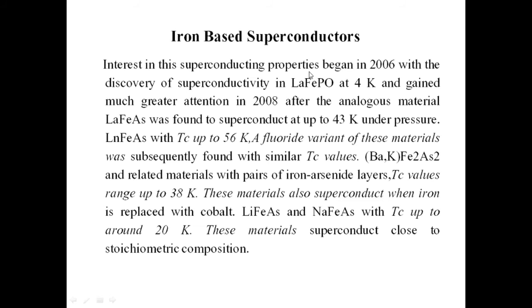Interest in these superconducting properties began in 2006 with the discovery of superconductivity in lanthanum FePO at 4 Kelvin, and gained much greater attention in 2008 after the analogous material lanthanum Fe arsenic oxide. Lanthanum iron arsenide was found to superconduct up to 43 Kelvin under pressure. Samarium iron arsenide has a critical temperature up to 56 Kelvin. A fluoride variant of these materials was subsequently found with similar critical temperature values.